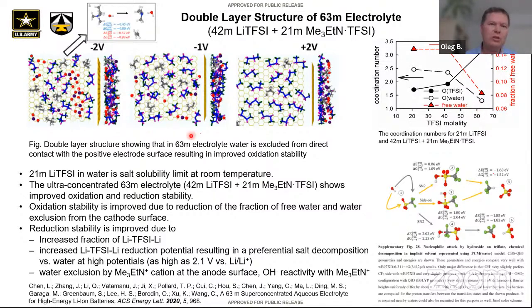So they did decrease the overall amount of water, but there was another positive benefit. Now we simulate this double layer structure, and we see much less lithium bringing in water for 2 reasons. First, there is less water, and second, there is a competition from ammonium cations, because they're also positively charged. These ammonium cations can preferentially scavenge when lithium comes with water and forms the hydroxide. Travis has shown recently that Hofmann elimination type reactions are favorable, so we can have an additional contribution to the SEI from decomposition of ammonium cations, in addition to what he has shown: slow reactivity through an SN2 pathway when OH comes to the triflate anion and decomposes, forming HCF3, which can further lead to highly fluorinated species.